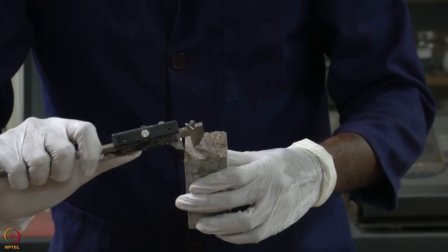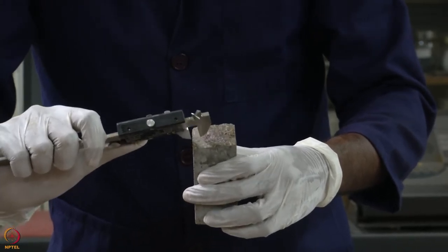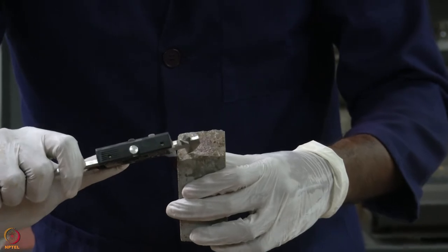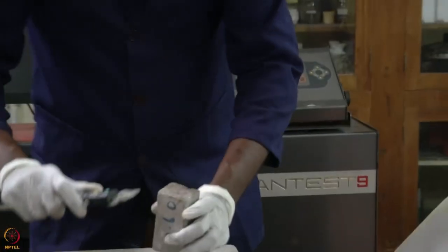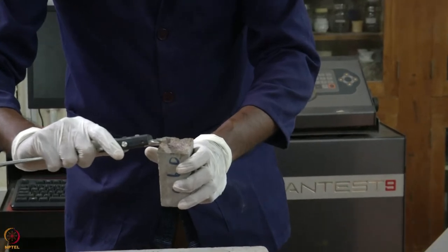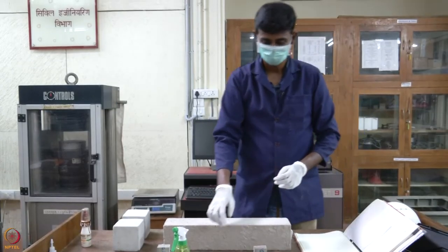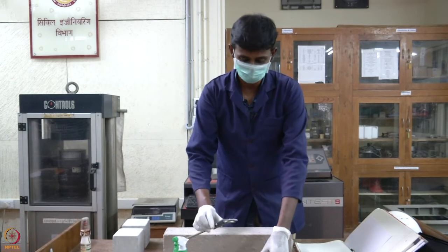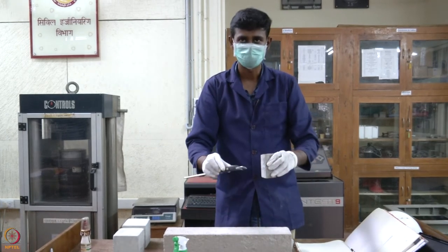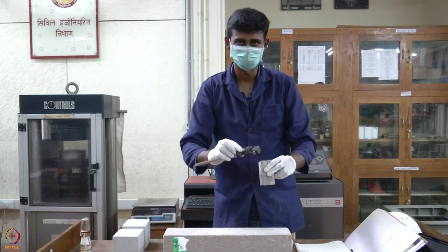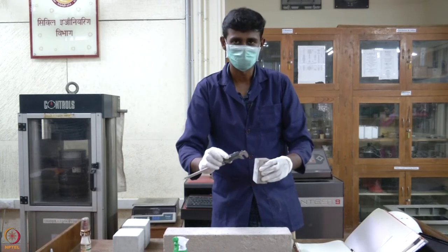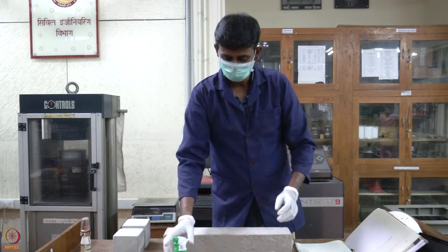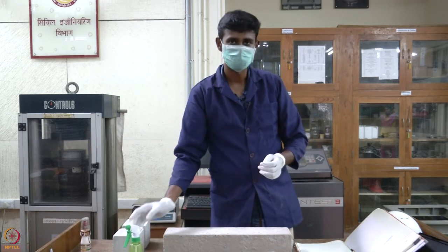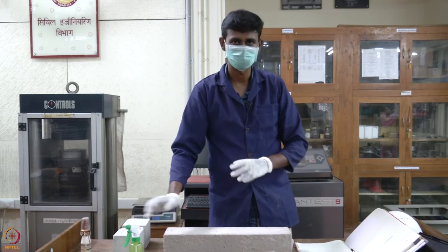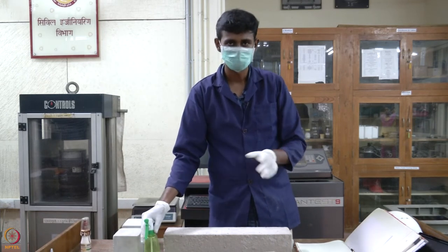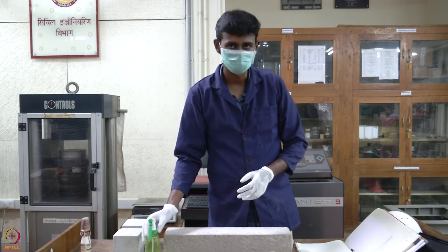Using the vernier calipers, I am now taking the measurements on each face. Similarly on all four faces of the mortar prism. From all four faces, I am getting a carbonation depth of 9.5. The mean value will be calculated based on the four measurements on all four faces of the concrete. While using a phenolphthalein indicator, it is recommended to always wear a mask and gloves, since it can be a carcinogenic agent. So it is always recommended to have a mask while doing this phenolphthalein indicator test.